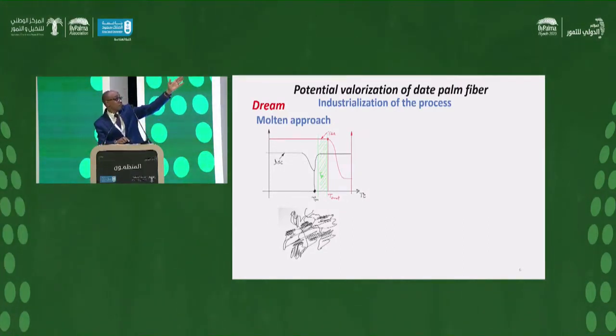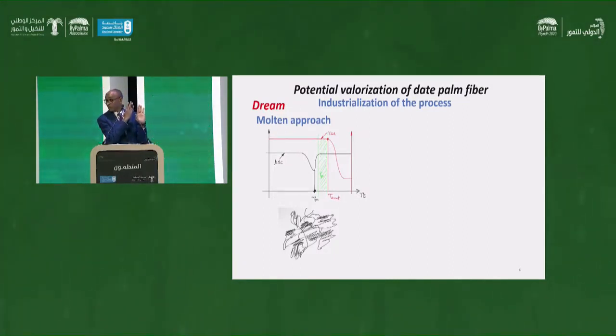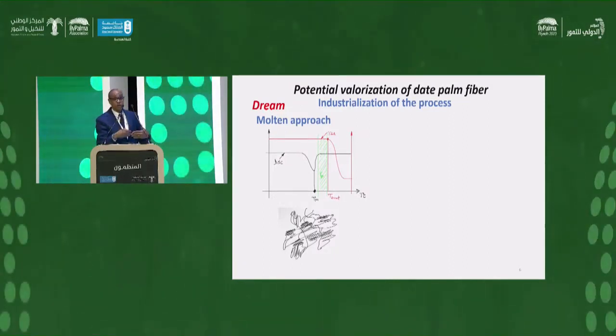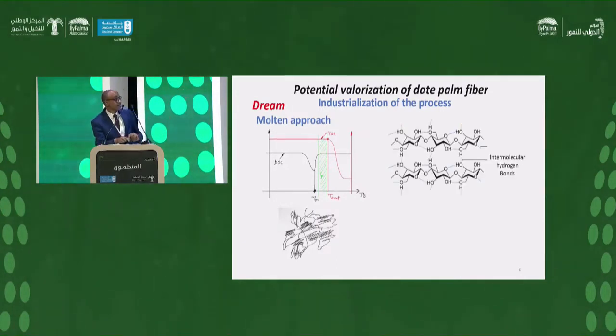And we have the degradation, the onset degradation of the materials, and the process temperature is chosen between the two temperatures. And we choose a temperature higher than the thermal molten temperature to reduce the viscosity. That's the approach when we use a standard thermoplastic. In the case of cellulose, we have the same shape.